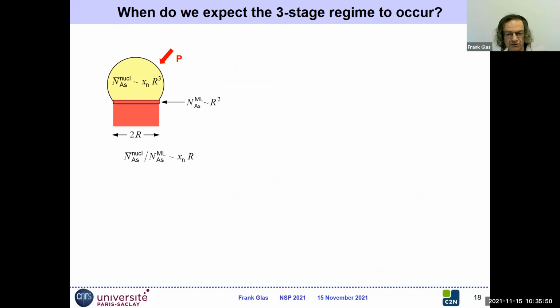So when do we expect this three-stage regime to occur? So now I come back to consider very simple considerations of size. So we may expect that the number of arsenic atoms at nucleation scales with the volume of the droplet, R to the third power, if R is the radius of the nanowire, times a kind of characteristic concentration where we have nucleation. So this will vary, but that's a kind of concentration. From this, we want to form a monolayer. And in this monolayer, of course, the number of arsenic atoms scales as the square of the radius.